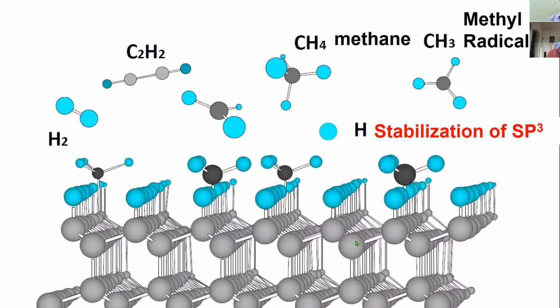So how do you get diamond from the gas phase? It's very simple, we can explain from this view graph, where the diamond surface is covered by hydrogen. The hydrogen is very important to stabilize diamond from a surface point of view, because it stabilizes the sp3 bond—it pulls against the graphite phase. Without hydrogen, what happens at the surface at high temperature is the surface becomes covered by graphene.